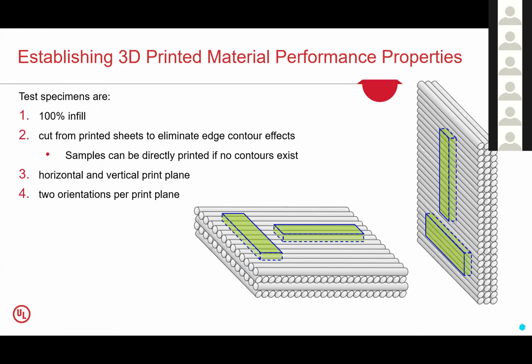We've also gone to cutting samples from a printed sheet. So whereas in injection molding, you may be directly molding those samples, now we want to print a sheet and cut off the edges because we do see, particularly with some of the techniques where you print the contour and then you infill the sample, that contour does play a significant role on the results. And yet we're trying to replicate what may happen in a different system, so we eliminate those contours. And what we'll report then on the blue card is, let's say for that horizontal plane, what is the lower of the two values? That's what gets reported on a blue card.